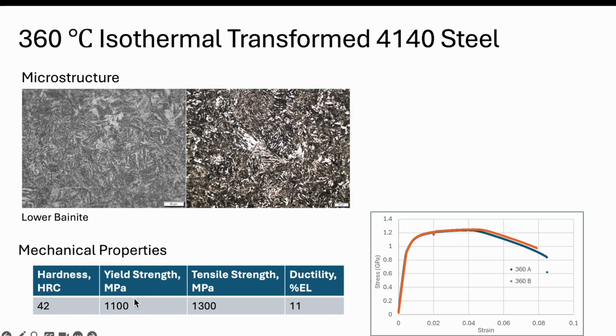The yield strength drops to 1100, and the tensile strength drops to 1300. And the ductility jumps up a little bit to around 11 or so. So again, the hardness is going down, the strength is going down, and the ductility is going up.